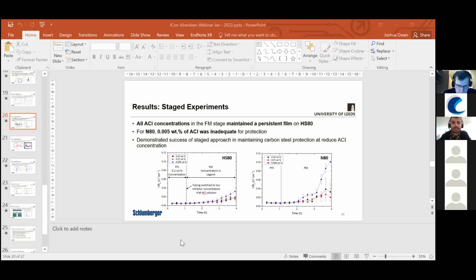Yeah, in some cases there is a minor increase. Evgeny has done work over longer periods, over 6 hours. In the particular case of interest, the injection period would be up to 6 hours, and then it would become a flowback challenge. And as I said, some of the work that Evgeny had done previously with the University of Leeds looked at the flowback effects, and we completed experiments over, I think, 24 hours with Evgeny and Ben. We looked at how the acid concentration changed over that period, and the corrosion rates that we measured using the same or similar acid corrosion inhibitors.